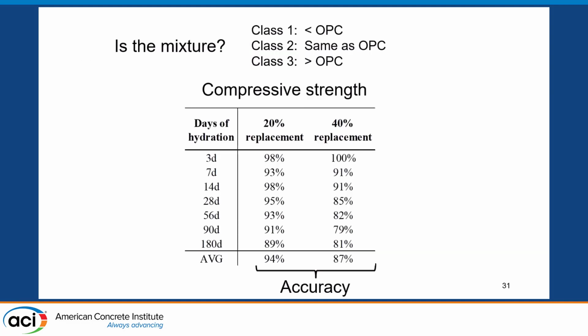So we got to ask this question. Is this mixture, again, is it in class 1, is it in class 2 or class 3? I know there's a lot going on this slide, but here's compressive strength, 20% replacement, and here's how accurate we were, 98% accurate at 3 days. Okay, and we dropped down here, 89% accurate at 180 days. That's a long time to predict, 180 days. A lot of stuff can happen, 180 days. Still, on average, 94% accurate. If I go to 40% fly ash replacement, right, here's where I fall, still on average, 87% accurate.